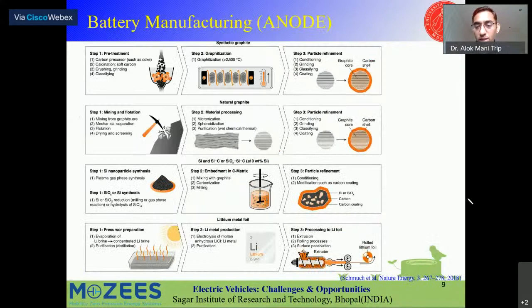Now, how is a battery made? That's another question. So I have explained the materials. Now, how are these materials made? I'm not going into the chemistry, just a very simplified flow diagram of this. So first, basically, we take the carbon. Carbon is used in the form of graphite because graphite has the layered structure. We can't use diamond. Diamond is also a carbon. We can't use coal, because of two reasons. Graphite gives the sp2 structure and has better electrical conductivity compared to the other two forms of carbon, and it has interlayer spacing, which facilitates lithium intercalation.